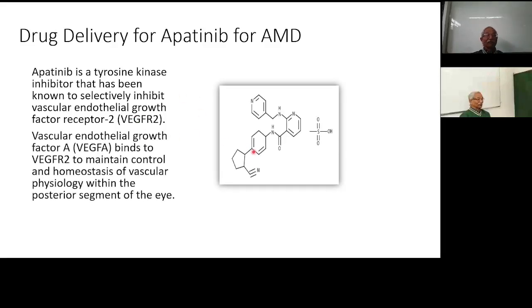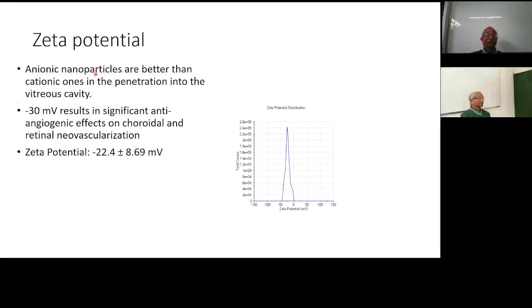Vascular endothelial growth factor A, VEGF-A, binds to VEGFR2 to maintain control and homeostasis of vascular physiology within the posterior segment of the eye. This is a typical structure of the apatinib for age-related macular degeneration. We use anionic nanoparticles, which are better than the cationic ones for penetration into the vitreous cavity. That is what we observed. And minus 30 millivolts results in significant anti-angiogenic effects on choroidal and retinal neovascularization. So you always have to have a negative zeta potential so that you will get better effects.